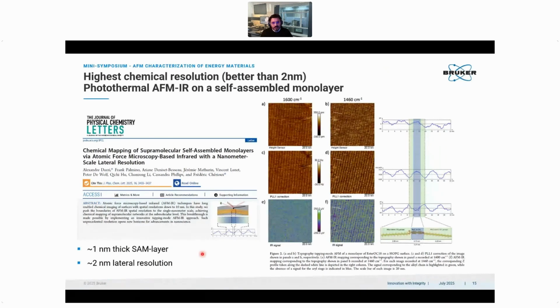So we are speaking about a film around 1 nanometer thick, so a very small amount of matter, of volume of matter. But we are still sensitive enough to this film, and we can measure the change of their infrared absorption properties. And you can see that when we look into the same area at different wave numbers, we have a change in absorption at a specific wave number and not on another one, indicating that this is basically chemical ID related contrast. Now, what's interesting is that if we take a profile, we have a change in the variation of these self-assembled monolayers. So these are molecules that are aligned, basically. We can see the discrimination, if you want, laterally speaking, with a resolution around 2 nanometers.